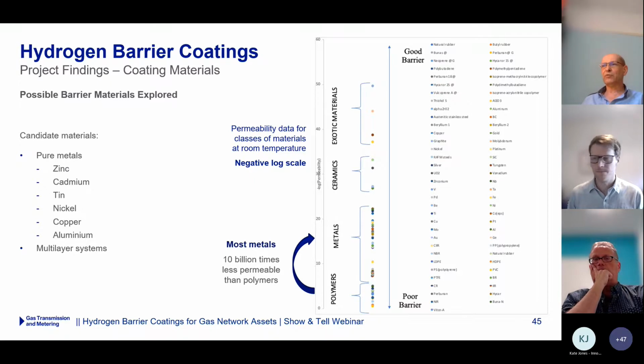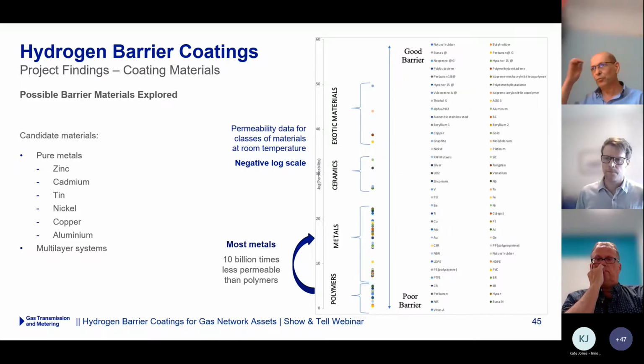They're brilliant, but they're not very useful for this kind of application. Of the practical materials, the metals provide significantly lower permeation values at room temperature than polymers, about 10 billion times lower. Of these, a subset of candidate materials was identified that we could apply with well-developed technologies and at an appropriate scale. These tend to be densely packed metals without their own hydrogen embrittlement characteristics that are readily available. Next slide, please.